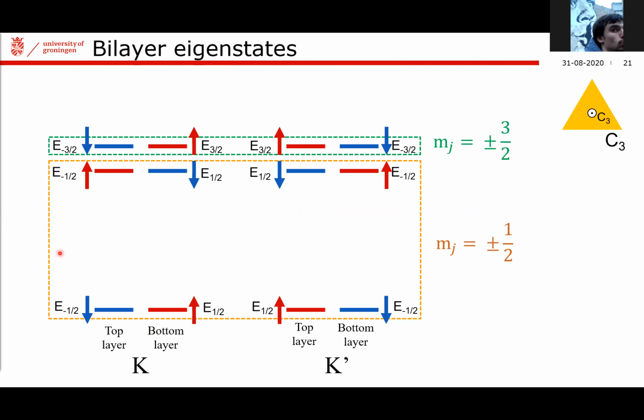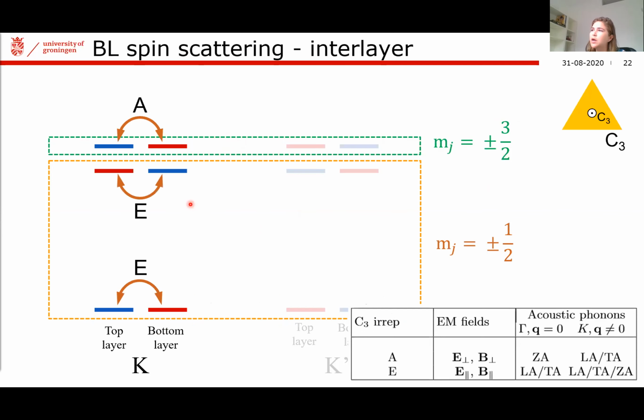Carmen, you have a couple of minutes left. Yes. So now if I look at the spin scattering processes, I will not look at the intra-layer spin scattering processes, because those are very similar to those of the monolayer, but I will look at the interlayer scattering processes, right? So now if I want to flip a spin up in the top layer into a spin down in the bottom layer, I can do that for the orange circled states with fields that transform as E, and those are electric and magnetic fields in the plane of the monolayer.